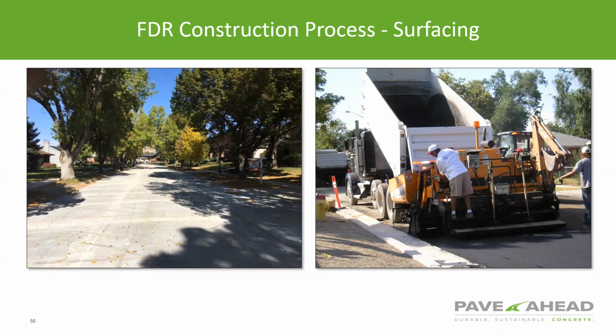That was also another thing I wanted to bring up on the surface things. Don made a comment that you can thin up your surface. And I agree, get the life out of the road, but you can also stage that budget. If you have the budget to do it, maybe don't do the surface layer this year. Maybe wait 5 years and do the surface layer, because you've got plenty of strength below, and maybe do 2 layers of surface instead of just one. So if you're going to get, say, 5 inches of HMA, maybe you do 3 inches this year, and then in 5 or 7 years, when you start to see a little bit of distress in that asphalt, do another overlay with that same exact budget and stretch that budget out longer, because you have that strength in the FDR down below.